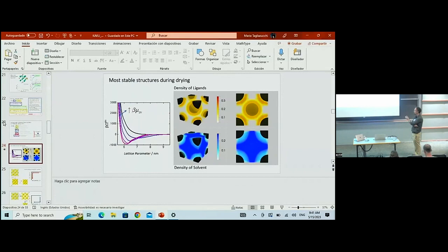This, of course, will depend a lot on the values that we use. For example, the lattice parameter will depend a lot on the size of the core. In general, we use particles that are a little bit smaller than in the experiments. I think these are 3 nanometer diameter nanoparticles, and we also change the length of the ligands to match the lambda parameter, so it more or less stays in the same range as in the experiments. So for that reason, these lattice parameters may be a little bit small.